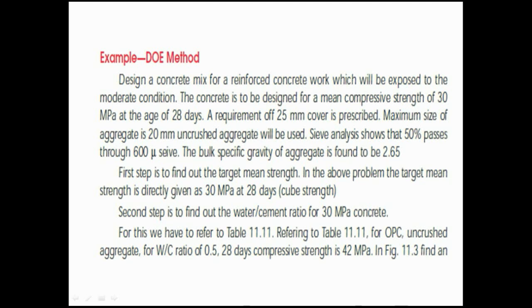In the numerical, they have given us: design a concrete mix for reinforced concrete work which will be exposed to moderate conditions. The concrete is to be designed for a mean compressive strength of 30 MPa at age of 28 days. A requirement of 25 mm cover is prescribed. Maximum size of aggregate is 20 mm and uncrushed aggregate will be used. Sieve analysis shows that 50% passes through the 600 micron sieve, and the bulk specific gravity of aggregate is 2.65.